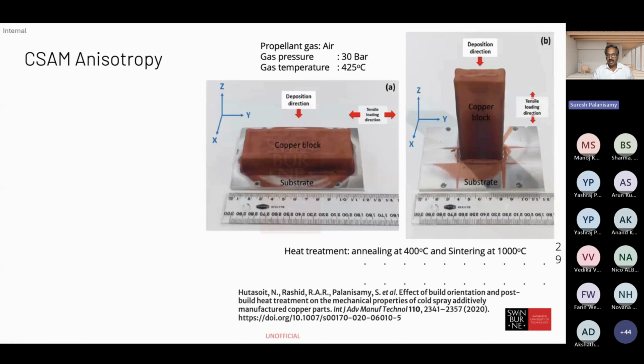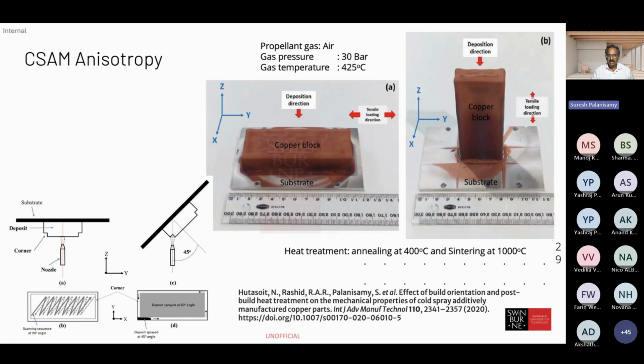And I've spoken already about anisotropy with the copper. The annealing temperature we used is 400 degrees centigrade and sintering around 1000 degrees centigrade. That's the temperature range we used there. The propellant gas pressure was 30 bar, and the gas temperature was 425 degrees centigrade in this case. When I say build direction, you can see the vertical build always happens. When it goes to the edges of the printed part, the robotic arm inclines and forms a 45-degree build angle.